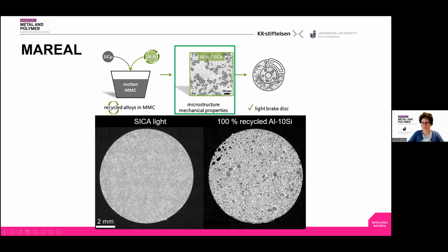We directly noticed, trying using 100% recycled matrix alloy, that the recycled metal greatly affects the distribution of the carbides in the microstructure, as you can see in this picture for comparison. So what we are looking into more is: does the difference in dispersion change the properties, and does it change them in a too damaging way, or can we still make compromises and accept these new properties? So how much are we affecting the properties of our material for the final application of the brake disc in mind?